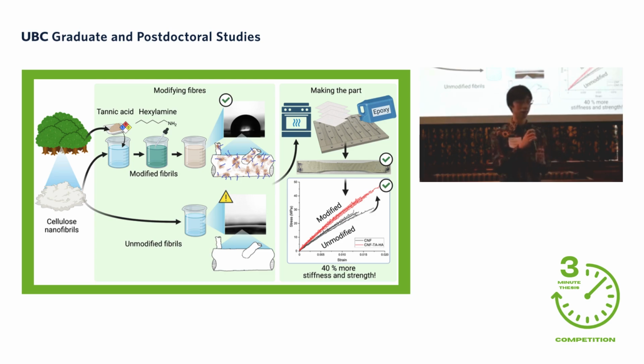Here's where my research comes in. I'm using another forest byproduct called tannic acid to coat the surface of these cellulose nanofibrils and chemically activate them, followed by a simple mixing procedure with hexylamine. It's a short-chain amine. What happens after simply mixing these chemicals together for a short time at neutral and relatively mild pH, we're able to coat the surface of the cellulose nanofibrils, as we can see in the picture, with amine chains that stick out radially from the surface.